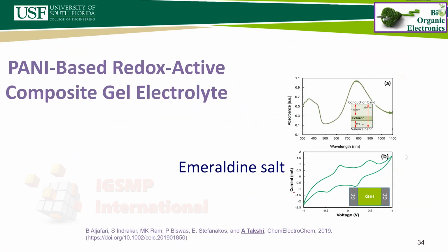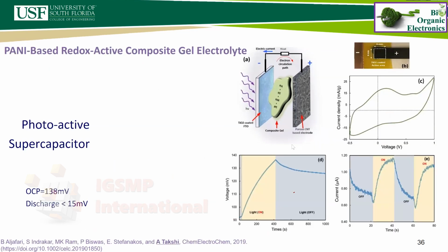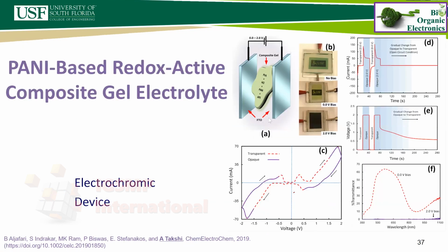And then, like spreading butter over bread, you can coat the electrodes, put the gel over that, and sandwich it with another electrode, and you have the hybrid device. And not only that, we learned that if we just put the gel between the two transparent electrodes, we can make an electrochromic device, meaning that by applying, let's say, 2 volts across it, we get a totally black color and opaque gel.